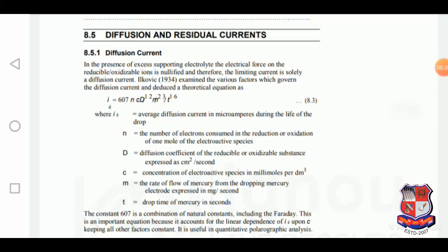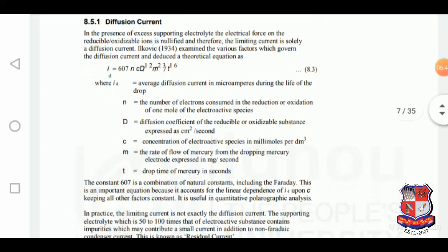Diffusion and residual currents. In the presence of excess supporting electrolyte, the electrical force on the reducible or oxidizable ions is nullified, and therefore the limiting current is solely a diffusion current. Ilkovic in 1934 examined the various factors which govern the diffusion current and deduced a theoretical equation as Id is equal to 607 n C D raised to 1 by 2 m raised to 2 by 3 and t raised to 1 by 6, where Id is equal to average diffusion current in microamperes during the life of the drop, n is equal